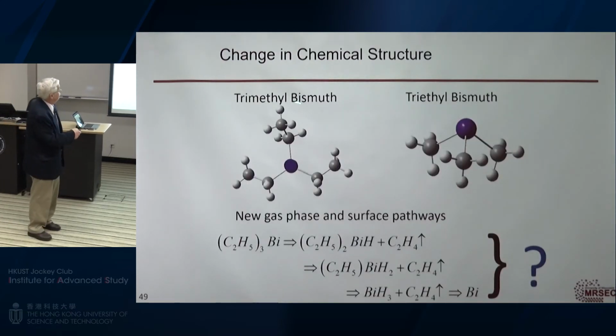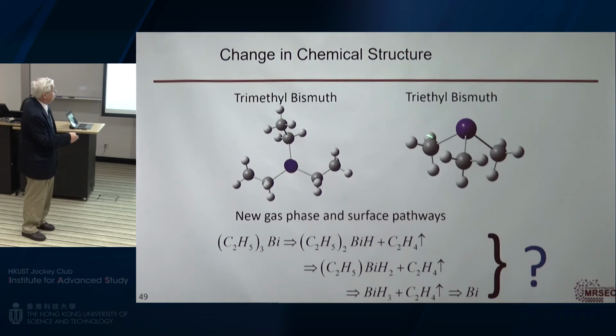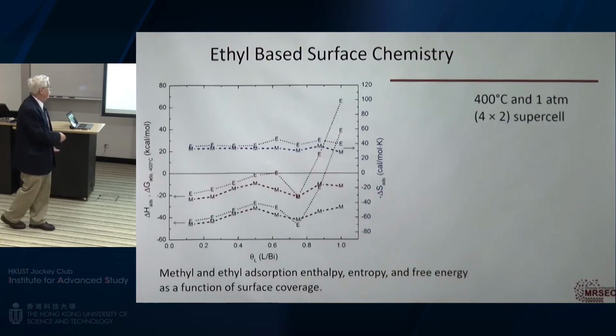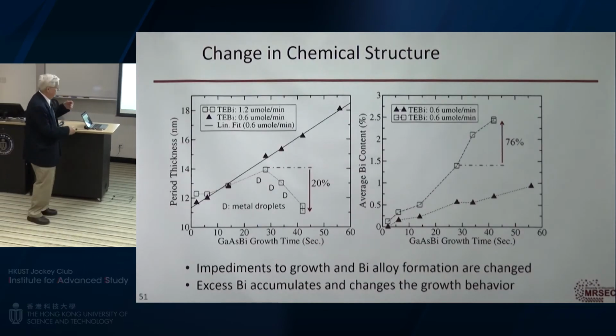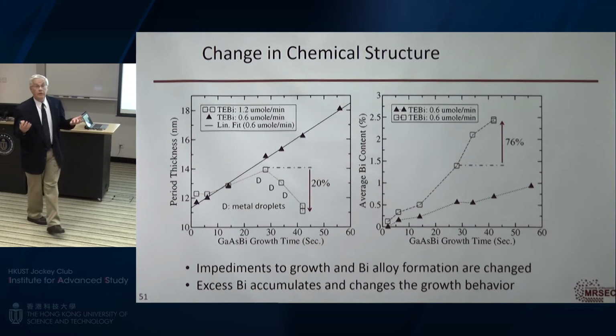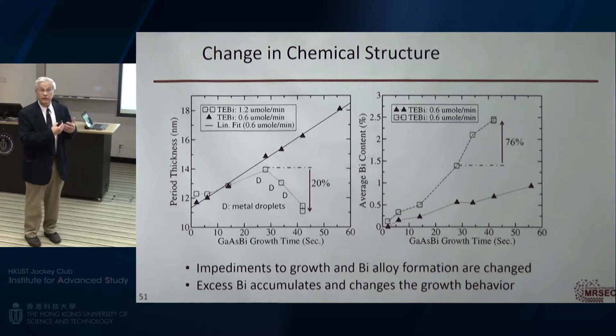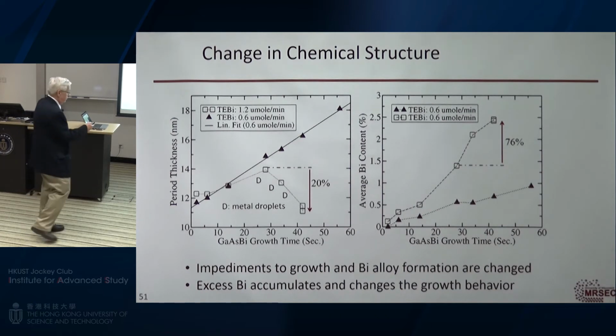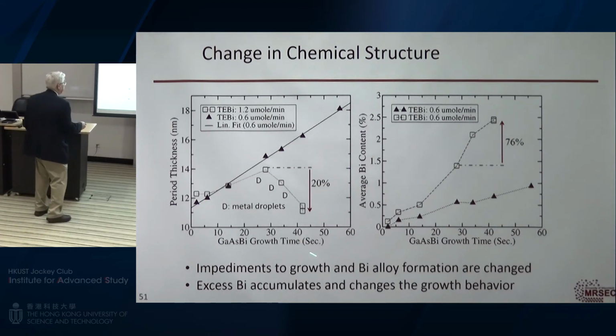So if methyl groups were preventing the growth of the material, we tried triethyl bismuth, and that has different reactions. And what we found is that if we used triethyl bismuth, the growth rate kept going with time. It had no methyl groups on the surface, so none of this was being blocked anymore, and so the growth rate continued. So the impediment to growth was removed, and the bismuth alloy formation was changed.